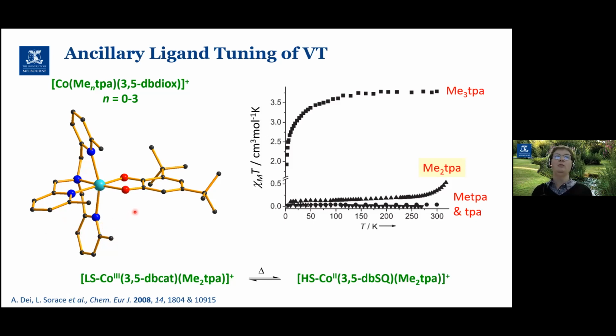In this family of complexes, the Florence team found that varying that ancillary ligand very much controlled the charge distribution in the complex and whether or not you saw valence tautomerism. Looking at the susceptibility over here, when we have just the plain TPA or the monomethyl TPA ligand, the profile is essentially diamagnetic and we're stuck in the low spin cobalt-3 catechol form across all temperatures. On the other hand, when you have 3 methyls on that TPA ancillary ligand, the chi-T profile is consistent with the molecule being in the high spin cobalt-2 semiquinone form, again, across all temperatures.